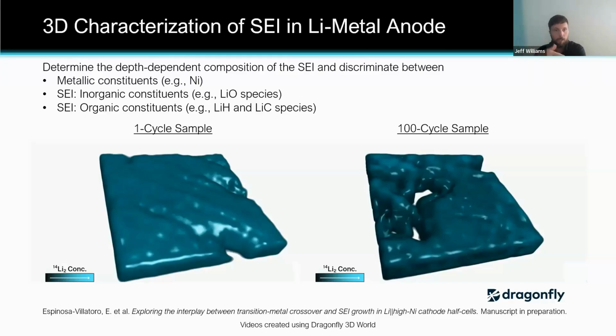And that is where we can take that to our advantage in this case, and like what Eric did in the work here, for being able to break that out between what is the LiO telling me versus the Li2O versus the LiC, for example. But to your other point, do we see this in the majors for nickel, manganese, cobalt? There's a couple of things there. One, these signals are generally much smaller, right? So whenever you do see a nickel, for example, coming up, you're going to have multiple isotopes that you are looking at in the mass spectrum, and you're not going to be flooded out by these organic compounds. These are generally more visible when you're looking at a clean mass spec. But when Eric was looking at the nickel here, it was very clearly nickel because there wasn't enough interference. So hopefully that answers your question.